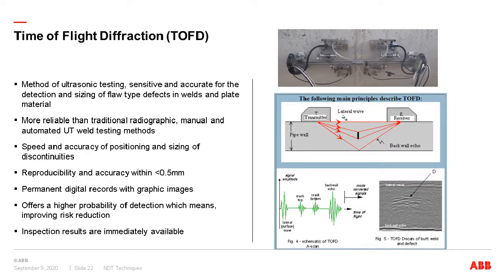Another technique, time of flight diffraction, TOFD. This is really for measuring flaws, things like cracks or features in parent metal. It uses ultrasound with a transmitter and receiver. It sends ultrasound, and when it hits the defect, it reflects back, and it can triangulate where that is, and it can size it very accurately, and gives an immediate report of where that is.